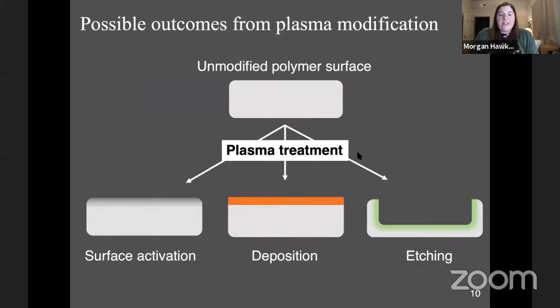So by carefully selecting and modulating these key parameters, it's possible to achieve different types of outcomes regarding what happens to the polymer surface upon plasma treatment. It's possible to activate the surface, which means essentially adding specific types of functional groups onto the surface. It's also possible to deposit a thin film on the existing polymer surface, and this is referred to as plasma-enhanced chemical vapor deposition. Lastly, it's possible to etch the polymer surface, which removes some material.